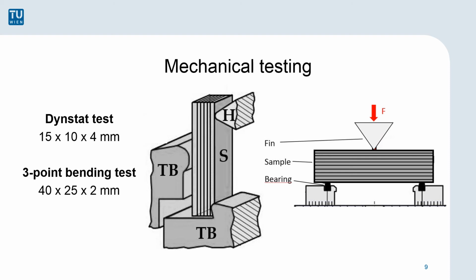To test the mechanical properties of the printed parts, Dynstat impact strength tests are conducted. This norm is chosen over more conventional ones like Charpy due to the limited space on the building platform. The samples have a length of 15 mm, a width of 10 mm, and a height of 4 mm. A total of 80 layers are manufactured to gain this height.